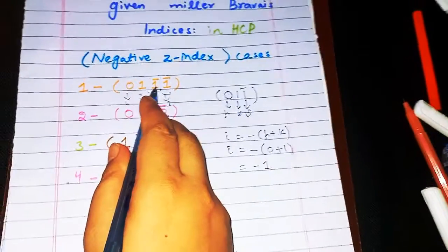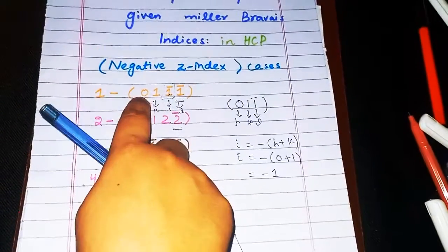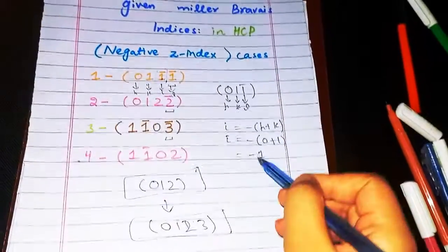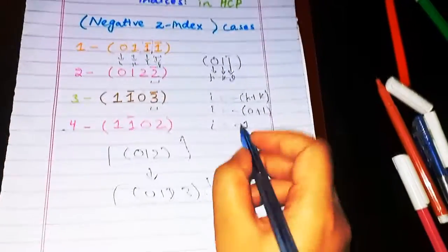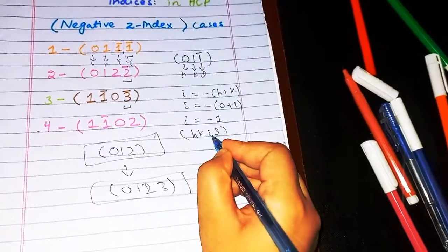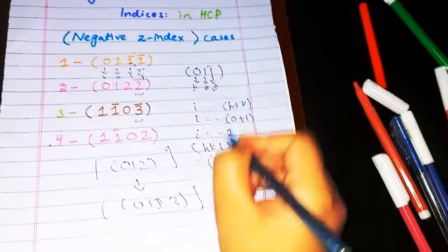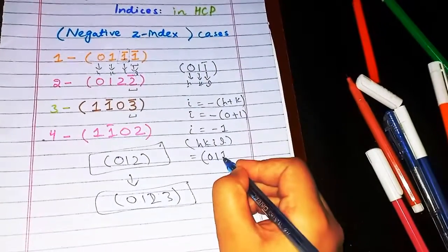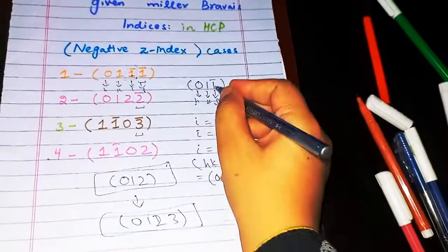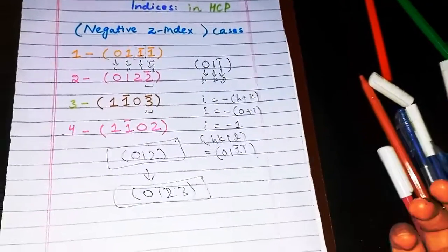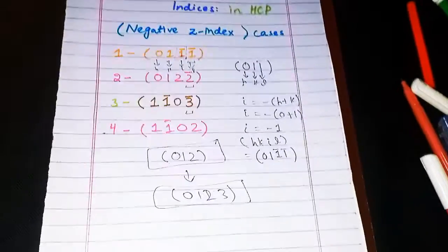I took H, K and L of this one, so I obviously will get I of this one. So this is I, and we can write these Miller indices as Miller-Bravais indices like that: H, K, I and L. I will be in between K and L, so we can write it as 0, 1 for K, and the I that we calculated, which is 1 with a bar on it. L the same. Simple as that. And you'll use the same method that I described in this whole video, and you can go with it. That is really simple.